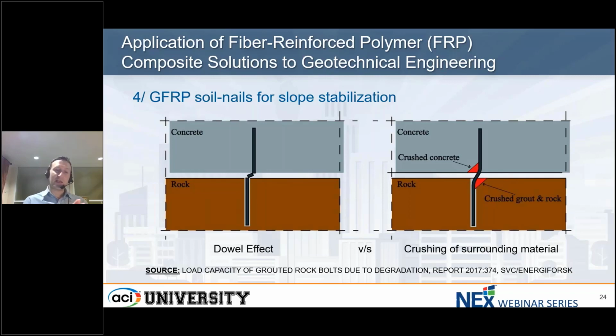This is really not easy to explain, because people feel we are turning around the properties of GFRP the way we want. What happens when you characterize the shear of an FRP bar in a lab through a typical ASTM transverse shear test? You're characterizing the dowel effect, what you see on the left side of the screen. This is the pure transverse shear applied to the FRP bar alone. So it's a very theoretical and pure shear test. In reality, when you install the system in the ground, that can be in rock, that can be in soil, before the system fails in shear, there will be crushing of the surrounding material.